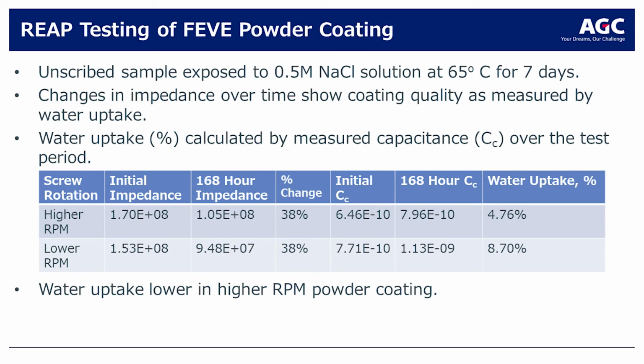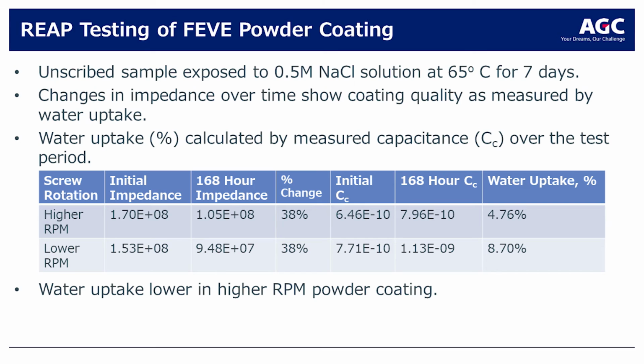Again, we exposed the sample to this sodium chloride or salt solution. We looked at impedance over time, measuring water uptake in this particular case. We calculate that from the impedance. We contrast here the higher RPM in the first row and the lower RPM in the second row. And in this particular case, you're looking for water uptake. What you see is that the higher RPM gives you less water uptake. That should correlate to the corrosion resistance of the coating.